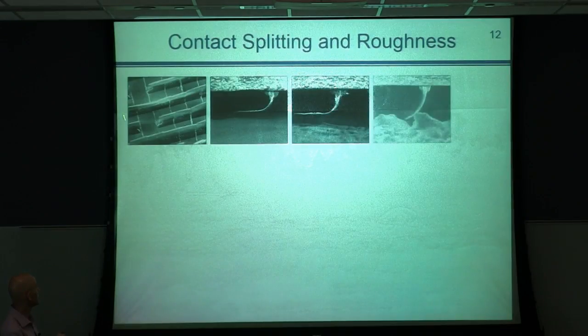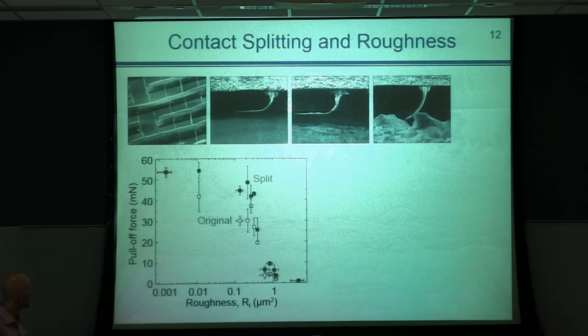So we used the same wall-shaped microstructures and cut them with blades to split long walls into much shorter sections. And we tested them against 12 or so different substrates having various roughnesses. What you see here is the same images of one wall-shaped projection in contact with different rough substrates. And this is the result.